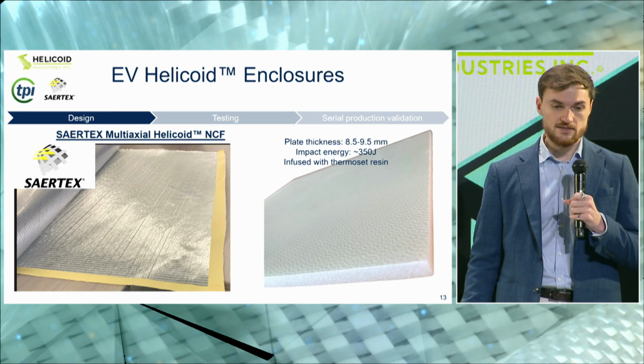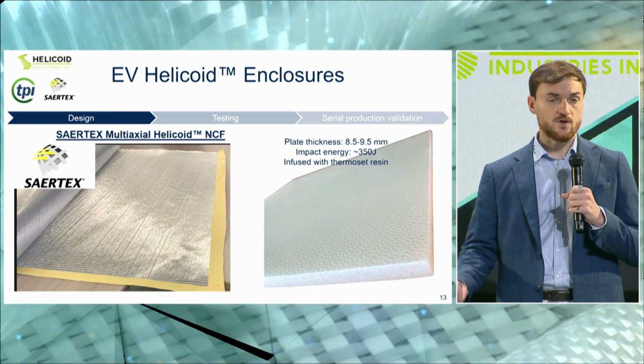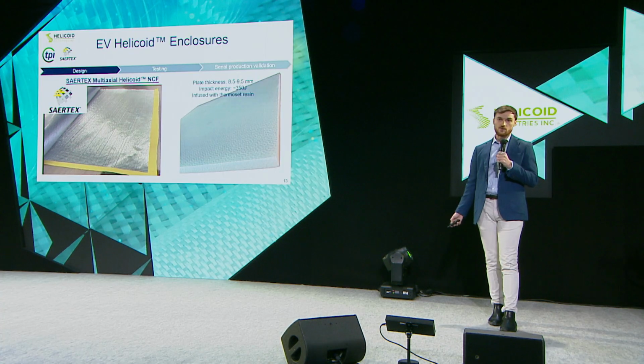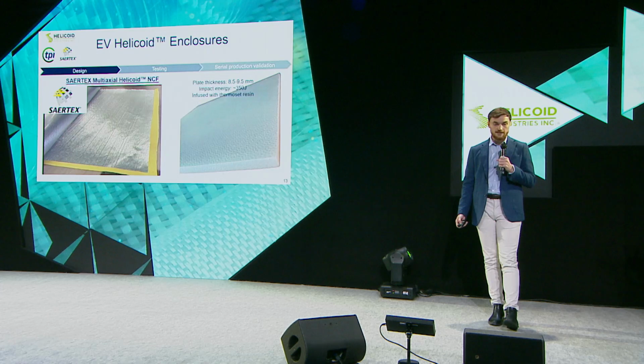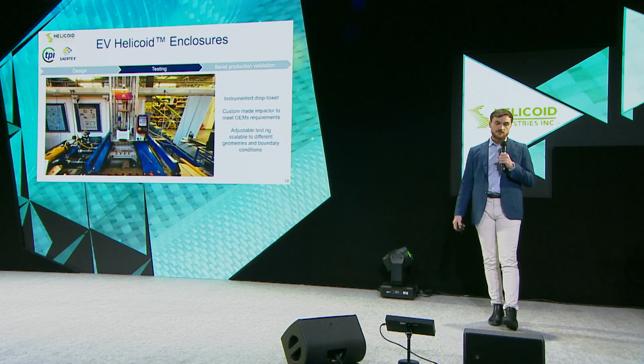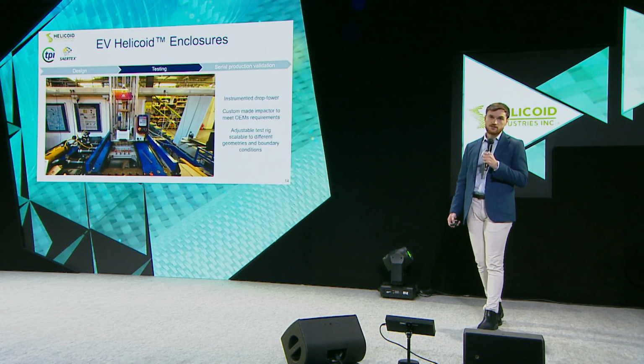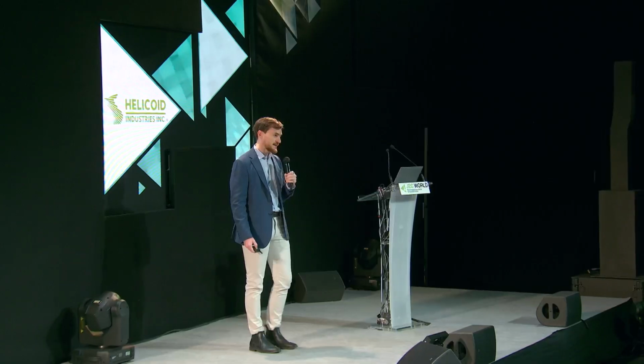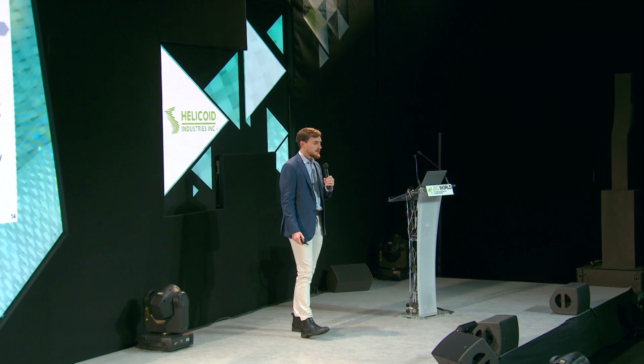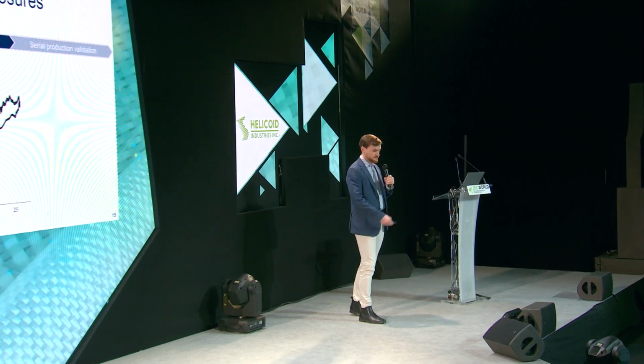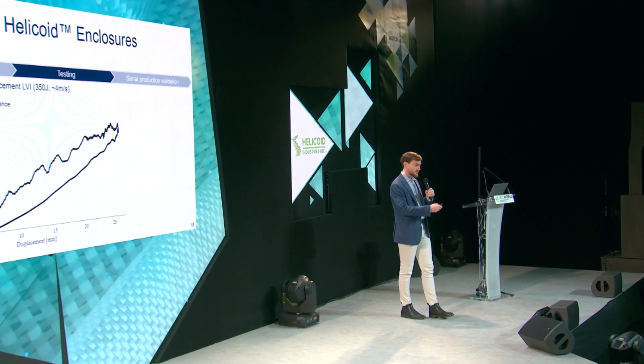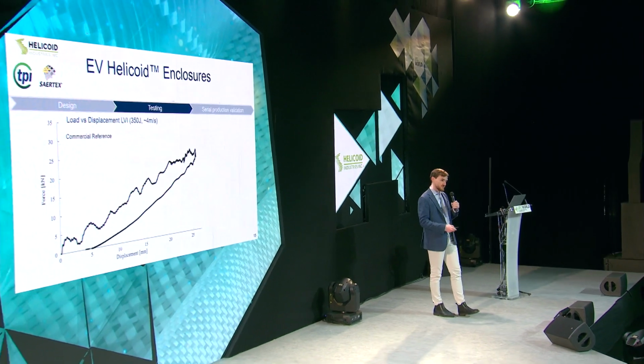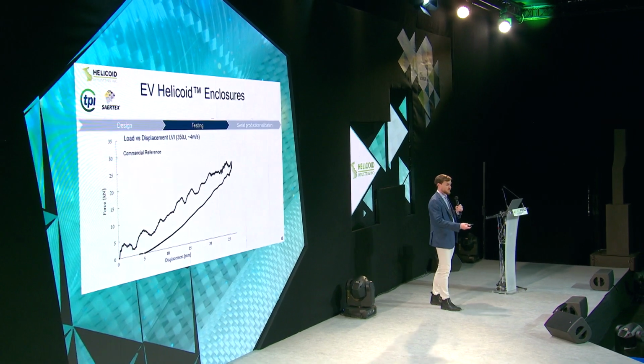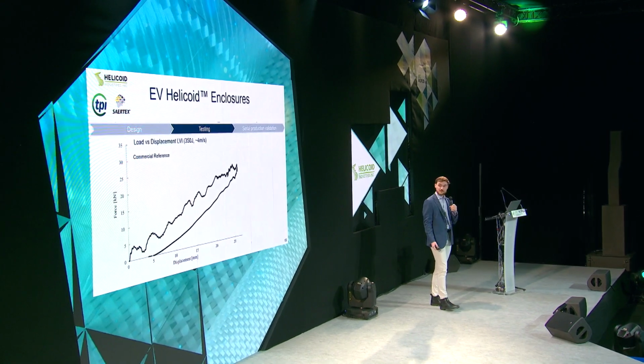We build the plates, infuse them, and then perform the impact test based on OEM requirements, in this case 350 joules of impact on the plate. We performed impact using an instrumented drop weight tower and a custom-made test rig, again based on OEM's requirements. And this is the type of results that you get. So you can get a full force displacement of the load history during the impact. This is for the commercial reference, doesn't say much by itself.